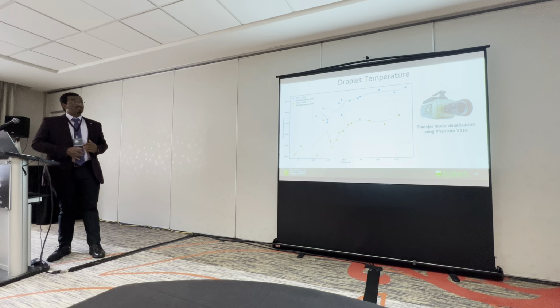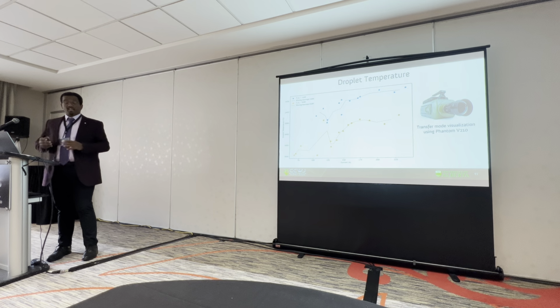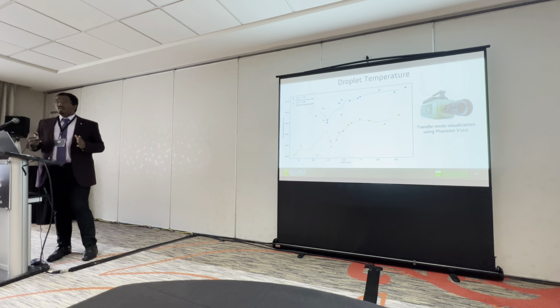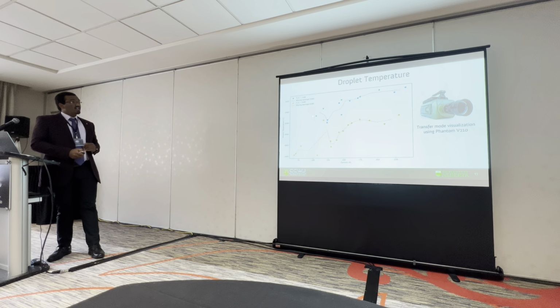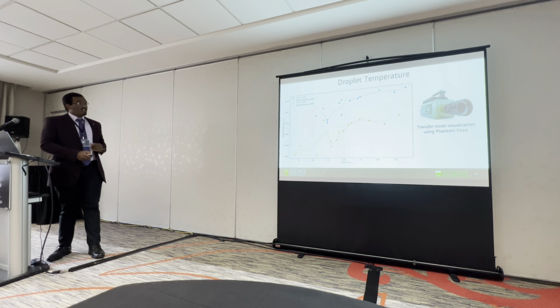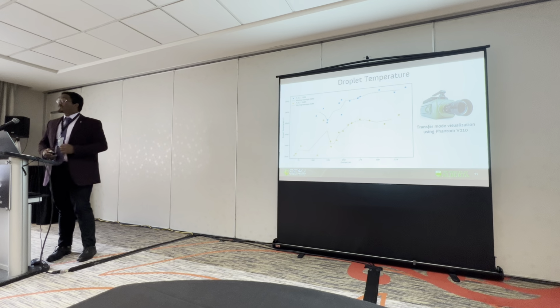Here we also use a high-speed video camera to understand the transfer mode during our process. We are able to see that over here, this is globular, moves onto a transition region, and becomes spray mode across the increasing current. In a similar scenario, we had globular, then a transition zone, and then spray after increasing current. Both these alloys have a very similar transition zone where they switch from globular to spray, and I found that pretty interesting.